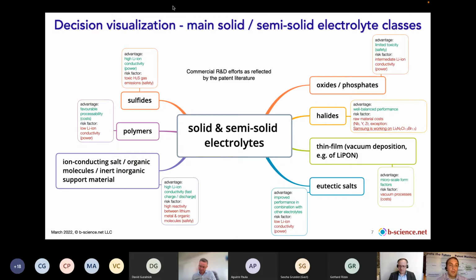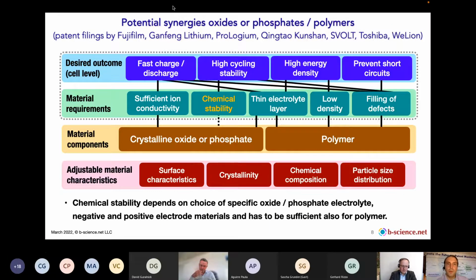And then there is also the approach to use still some liquid electrolytes together with ion conducting salts in an inert support matrix. So here it's not fully solid, but the target is usually to harvest most of the benefits of solid components combined with some liquid components that usually provide high lithium-ion conductivity. So this was an overview.